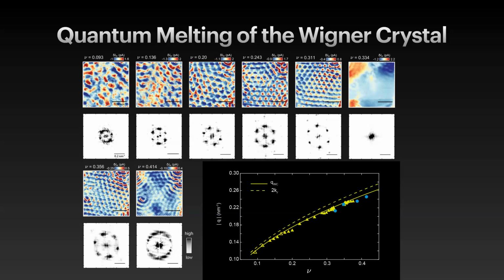So what I was going to get at is these points near the 1/3 and 2/5 states. If you look at the FFTs, you would see signals that look like this one. It will have a liquid looking like the features in the data. It has a characteristic length scale and no orientational degrees of freedom, which in the structure factor just comes up as a ring. And what's interesting is that this Q vector describing this ring is the same Q vector that you would have if you had a Wigner crystal at that density, even though you don't have a crystal. You have something that looks like a liquid.